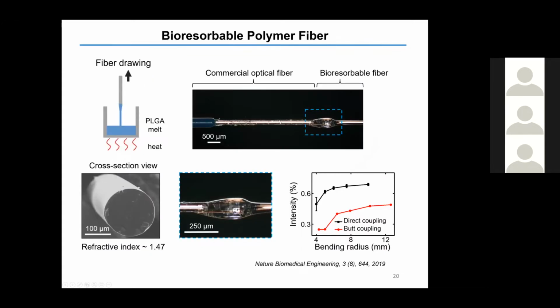So we produce those bioresorbable fibers based on a simple drawing process, applied to the bulk preform heated to a temperature around 200 degrees Celsius to yield the PLGA core. And we can use the tip of a commercial fiber as a lead for the fiber drawing process, which directly couples the resulting bioresorbable fibers to the commercial fiber in order to minimize coupling loss at the junction areas.